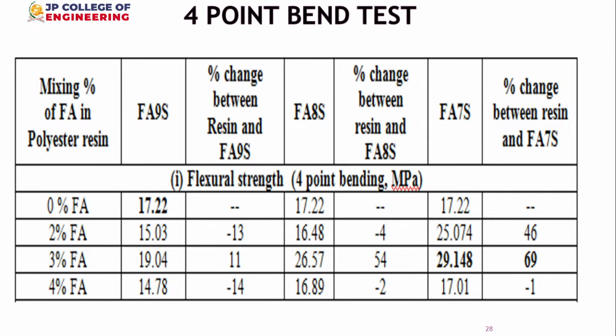But if you add only a little amount, 2%, strangely the strength comes down. The reason being it may introduce some amount of void, or it may initiate the crack sooner, so that the failure occurs. But for 3%, you can see the increase in the strength. Again, if you increase further to 4%, it decreases. So overall, the additional 3% gives the better value.